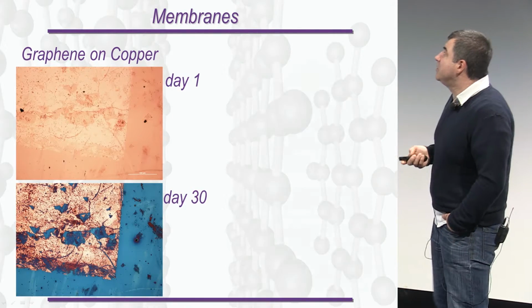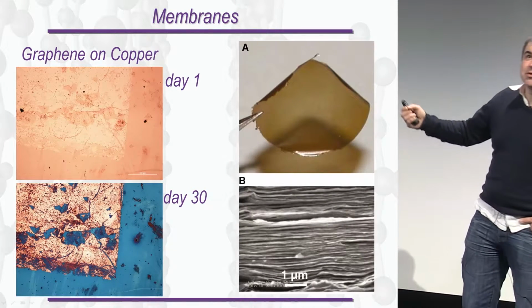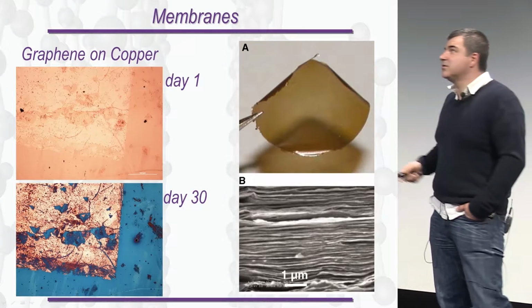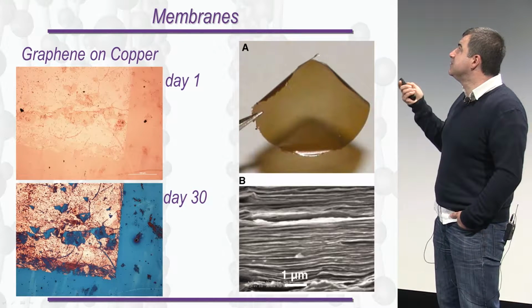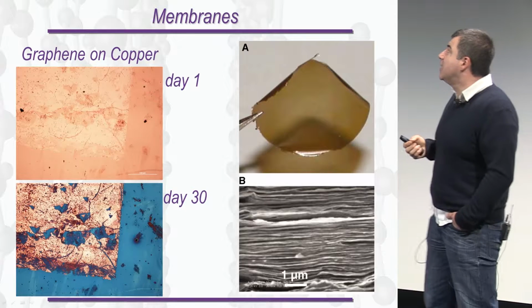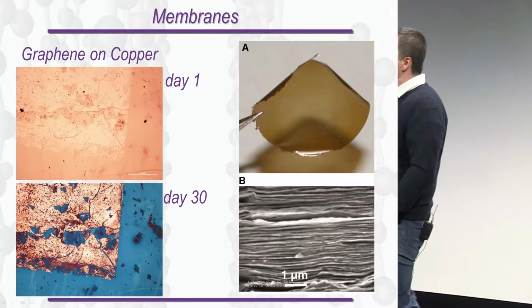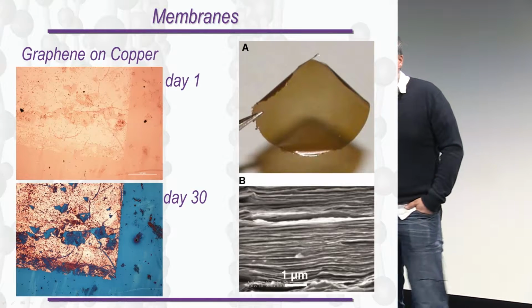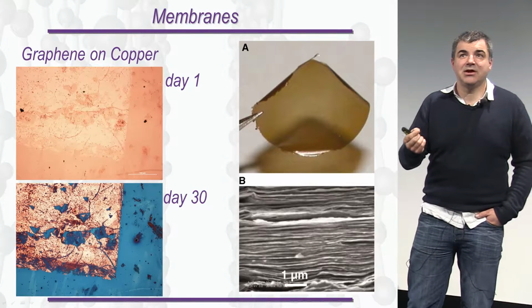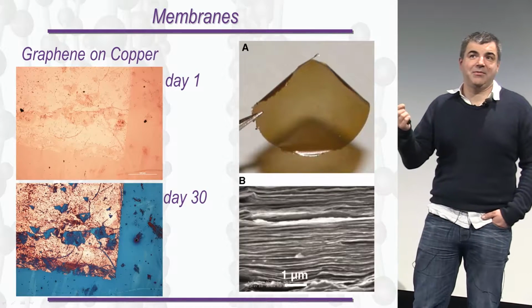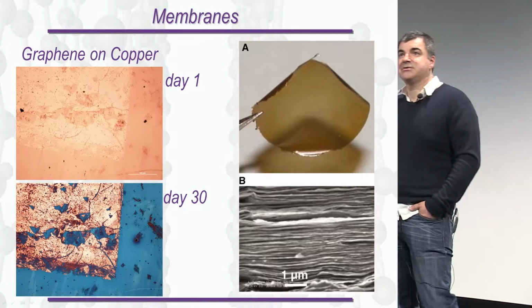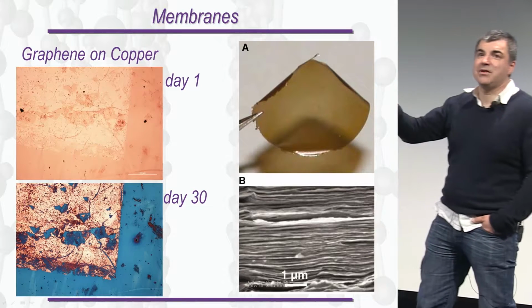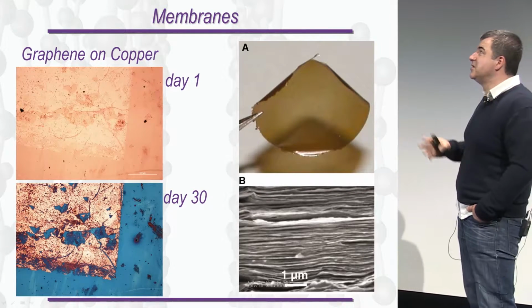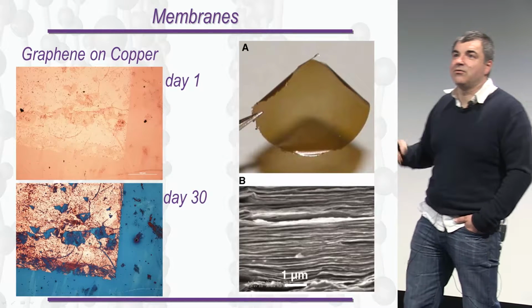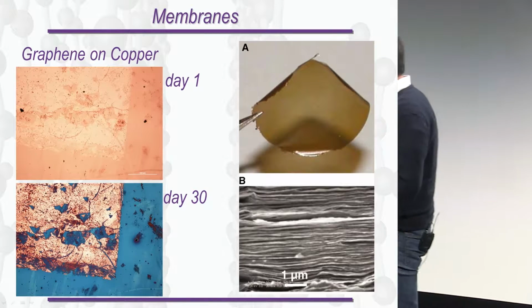For example, you can grow it on top of copper, and everywhere copper is protected by graphene, it doesn't corrode. Or one of the cheap ways to produce graphene is through graphene oxide. So this material is called graphene oxide paper, and it has this very unique property that it doesn't allow anything through apart from water vapor. So a water molecule comes in, opens a pore and passes through, but nothing else can go through.